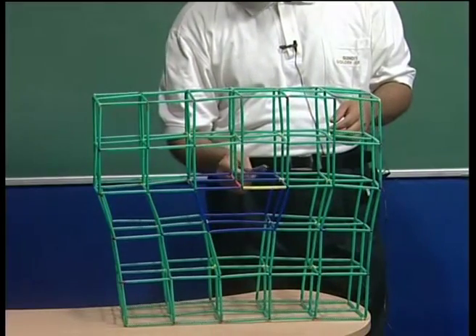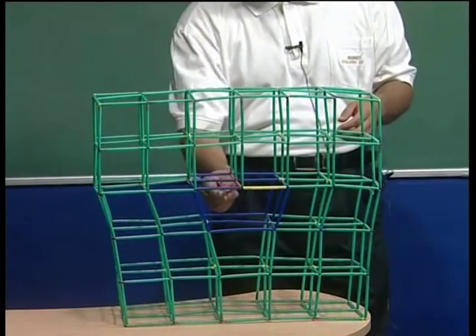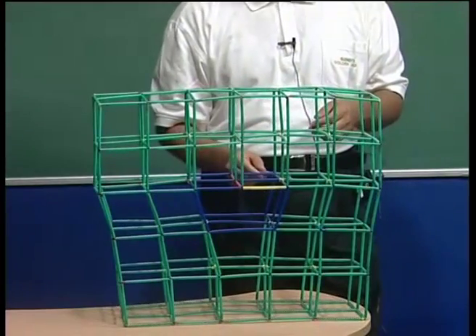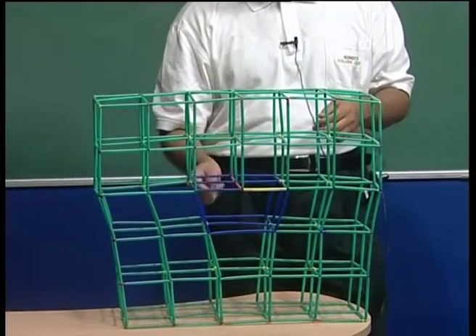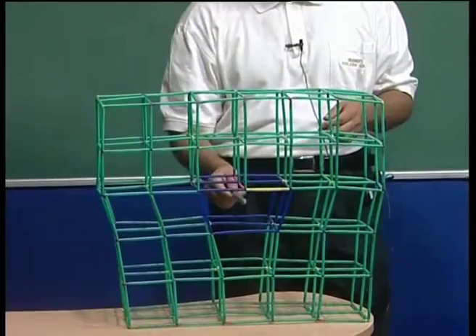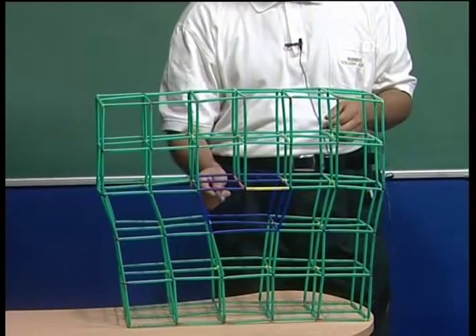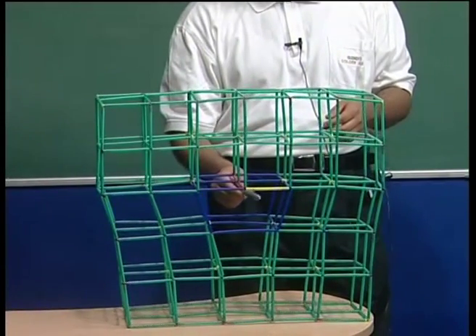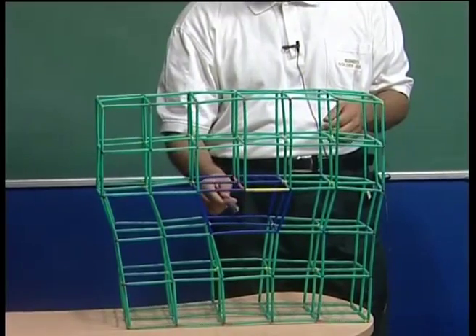And this region of the dislocation, which has been marked in blue, you can see here blue, is the region which is highly distorted. That means the bonds in this region are highly distorted and the crystal is highly distorted. This is the region wherein the stress fields and strain fields are very large.